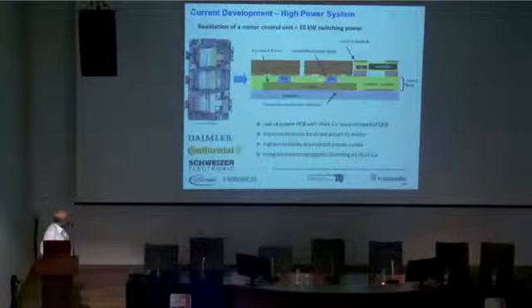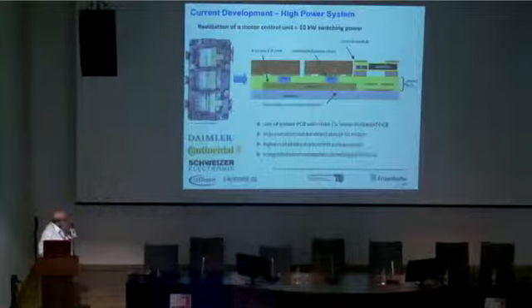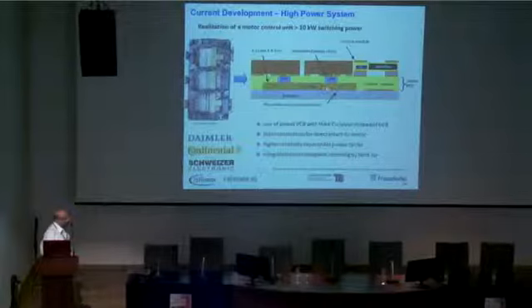So we had a lot of IGBTs that can handle a lot of voltage. These IGBTs come with a silver interface at the bottom and also with aluminum. And the concept we developed here was very interesting. We started using very thick copper because in power applications you really need to dissipate heat very effectively. And you assemble these IGBTs using a kind of silver sintering adhesive, which has about 150 watt per meter Kelvin. So in this way, you promote the heat dissipation, also in the Z direction from here.